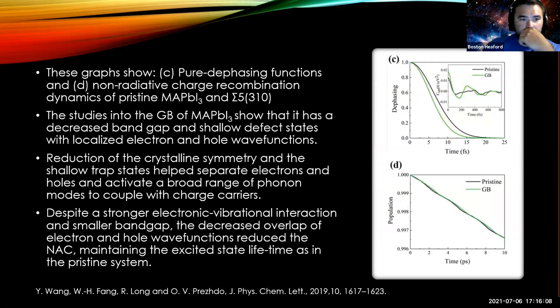And it was found that the grain boundaries of the methylammonium perovskite have a decreased band gap and shallow defect states with localized electron and hole wave functions. And the reduction in the crystalline symmetry and the shallow trap states helped separate electrons and holes and activate a broad range of phonon modes to couple with charge carriers. And despite a stronger electron-vibrational interaction and smaller band gap, the decreased overlap of the electron and hole wave functions reduced the non-adiabatic coupling, which maintained the excited state lifetimes in the grain boundary system as compared to the